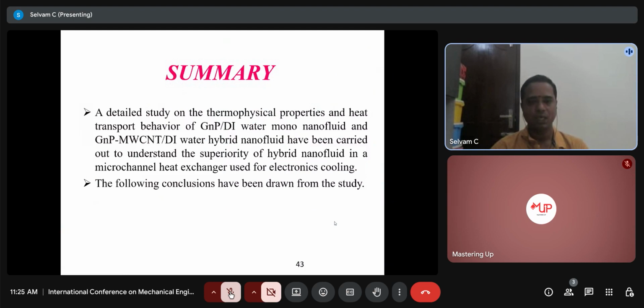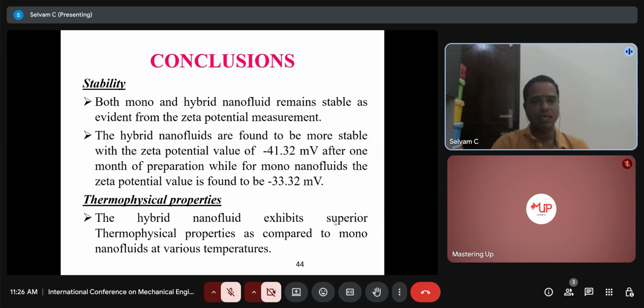We have studied the performance of a heat sink for electronic cooling application with the use of graphene nanoplatelets and deionized water as a mono nanofluid. After that, we tried the graphene multi-wall carbon nanotube DI water nanofluid, which is called hybrid nanofluid. With respect to stability, both nanofluids show better stability, but compared to mono nanofluid, hybrid nanofluid shows a higher zeta potential value, so it has more stability.